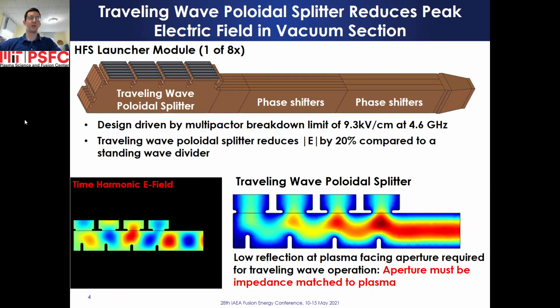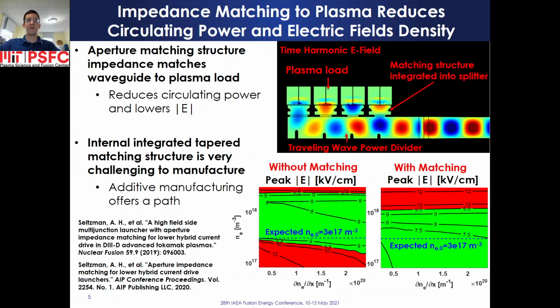A traveling wave poloidal splitter reduces peak electric field in the vacuum section of the launcher. This design is driven by the multipactor breakdown limit of 9.3 kV per centimeter at 4.6 GHz. Elimination of standing waves within the power splitter reduces electric field by 20% compared to a standing wave power divider. For optimal field reduction, low reflection from the plasma is necessary, requiring the output apertures to be impedance matched to the plasma surface. Although circulating power within a multijunction reduces power reflected to the RF source, the standing waves within a launcher increase electric field, limiting power handling capability.